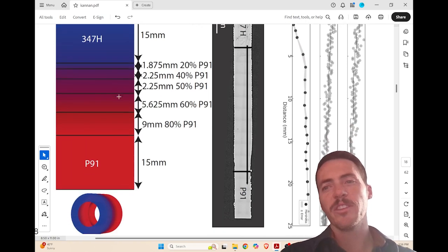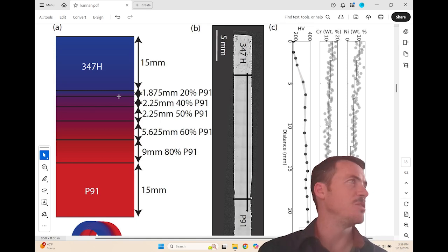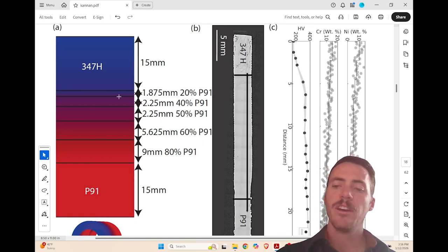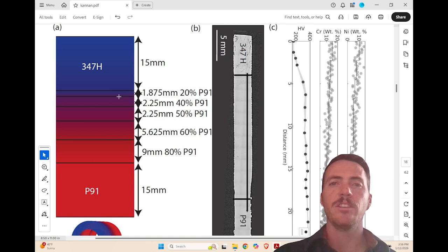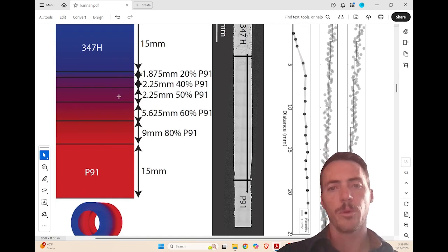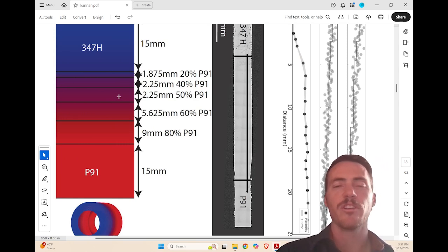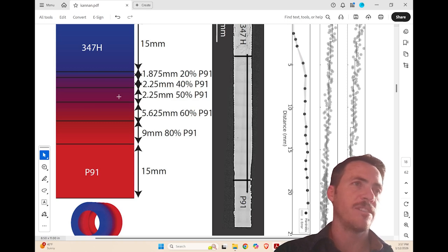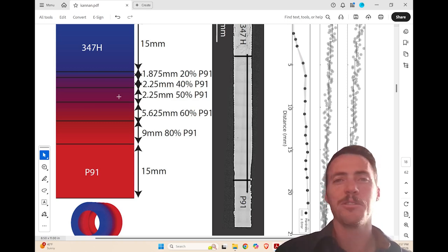When you look at these transition curves shown on the far right, you see that it actually works. You essentially do have this nonlinear design giving you the hardness across the material, across the graded zone, and a defect-free transition region, as you see in the micrograph there. So ultimately, what I think we see in this paper is a powerful demonstration of the ICME method, a clever approach of tackling a fundamentally nonlinear problem with a series of nonlinear solutions. And I hope you'll check it out in the latest issue of IMMI.